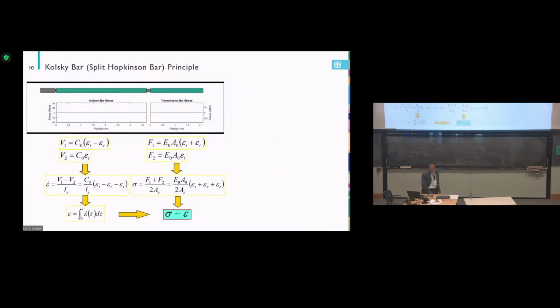So here's how the Kolsky bar or split Hopkinson bar works. No matter whether you use a gas gun or whatever, you shoot a striker, the short rod, that's a projectile. We shoot this projectile at a long rod, which we call the incident bar, generating a stress wave propagating through this long rod. When the stress wave propagates to the specimen here, part of this wave is reflected back as a reflected pulse, and the rest is transmitted into the transmitted bar. Now here, this is the slide I mentioned.